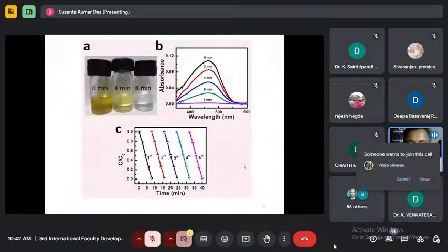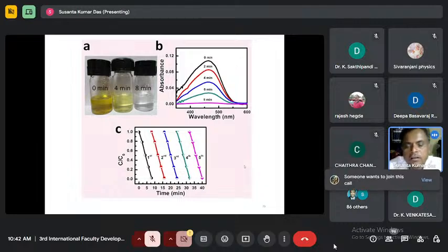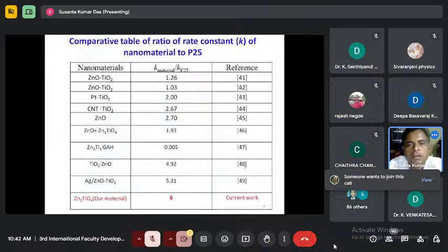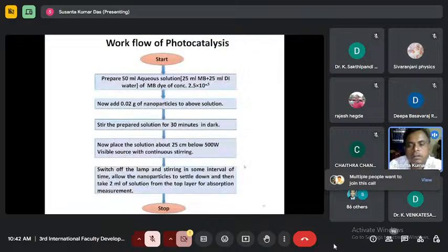Then we went for the recyclability study. Again, the reviewer had asked us to go for a recycling study, to see how many times it can be recycled, and we found the material can be used up to 5 cycles. We found an almost similar result, and that we have reported in one of our publications. In that we found that this material can show 6 times higher activity than that of P25, and we compared with different other materials. That was published in Jalcom actually.